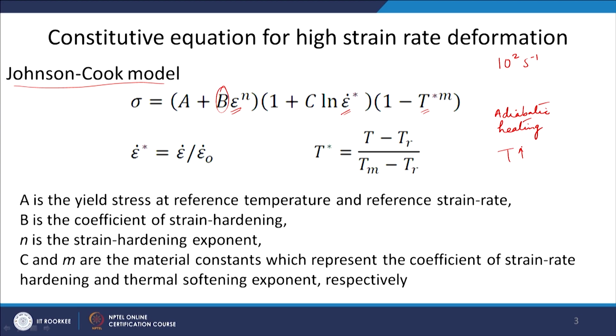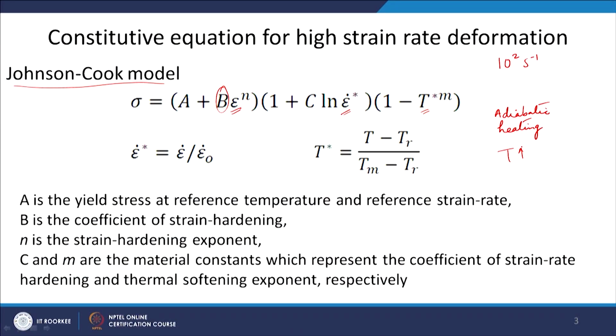So, for example, you have set the temperature of deformation as 900 degree Celsius, and you are doing a very high strain rate deformation. What will happen? The temperature will rise to 950 degree Celsius. I am just taking an example. Now, this 50 degree rise, you should understand that temperature will always come in the exponential term. Okay. So, stress is dependent exponentially on temperature. So, linear rise in temperature will give an exponential rise in the, or in this case exponential drop in the